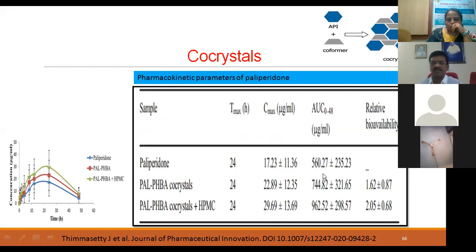And AUC was also increased from 560 to 744 with the co-crystals and from 560 to 962 in the presence of the HPMC. So when bioavailability was observed, bioavailability was increased by 2.05. Relative bioavailability of paliperidone prepared in the crystal form in the presence of the HPMC is not enormously, but increased to some extent. It was an initial study that we have carried out, and there is an improvement of the bioavailability.